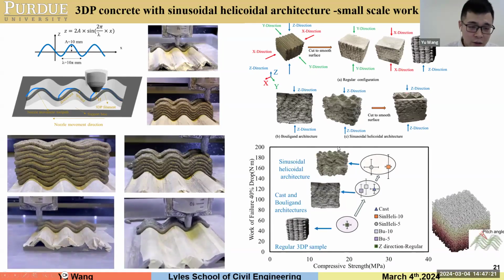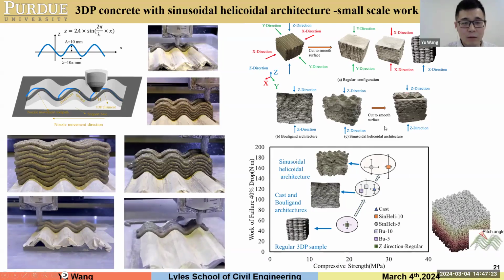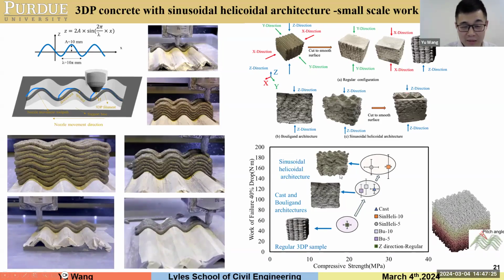And we also ran some mechanical testing at small scale, and we tested the helicoidal architecture, cast sample, and Bouligand architecture. We found that the helicoidal architecture performed really well on compressive strength and work-of-failure. It can improve both of the properties. So this brings us an opportunity to scale it up to test the energy absorption capacity of this architecture.